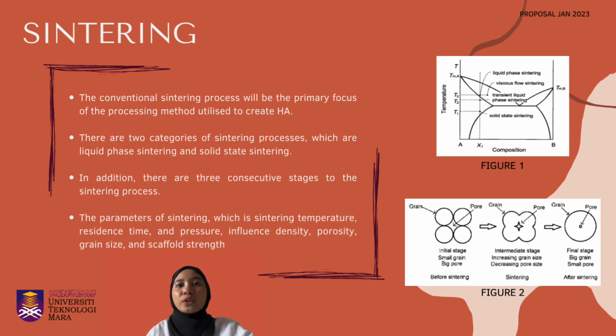which creates the continuous phase, and it finishes when the pores become separated. In the last stage, the isolated pores may totally vanish, producing a fully or nearly fully solid ceramic. Moreover, the parameters of sintering, which are sintering temperature, residence time, and pressure, influence density, porosity, grain size, and scaffold